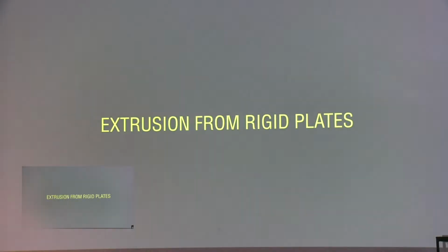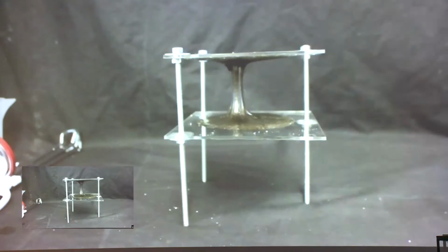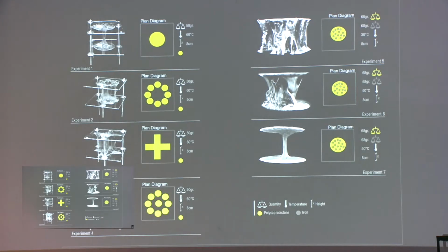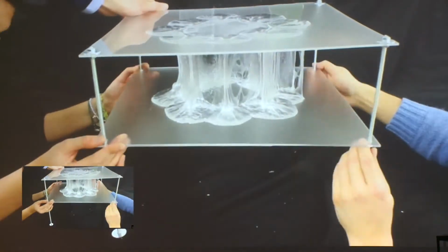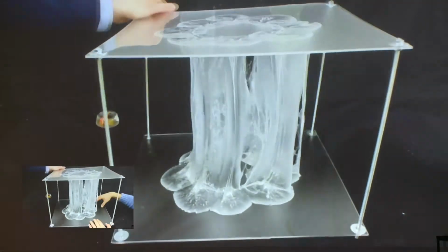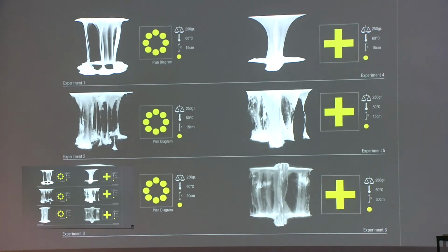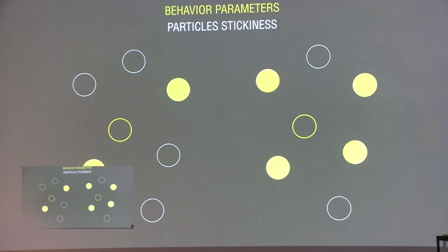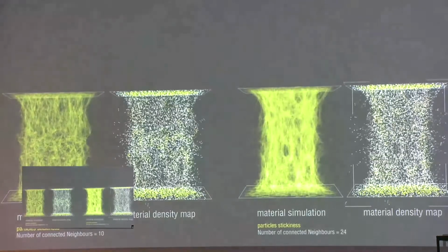In the first experiments, we did small-scale experiments trying to fuse the material with other materials and looking at the parameters of temperature and quantity, and then trying to scale up the most successful experiments and looking again at the parameters of temperature versus quantity. The physical experiment showed us that many parameters are involved in the material formation. For this reason, we developed a material simulation that allows us to study these parameters individually.